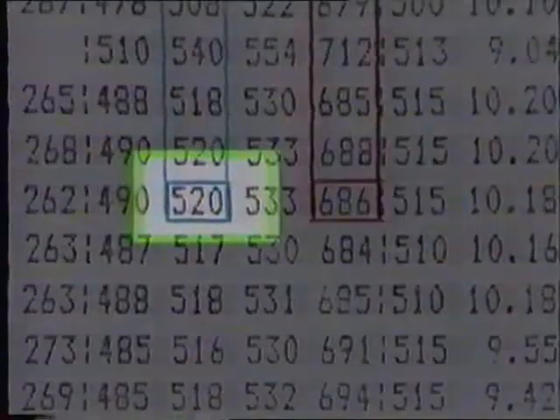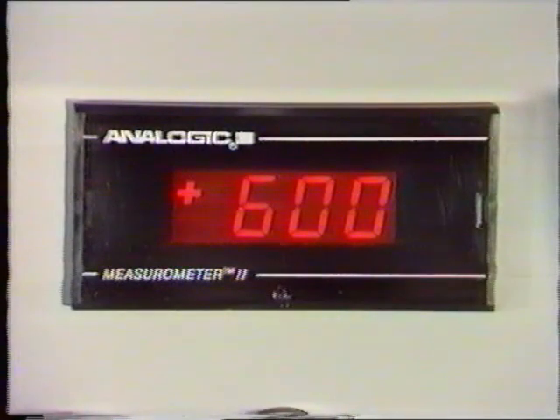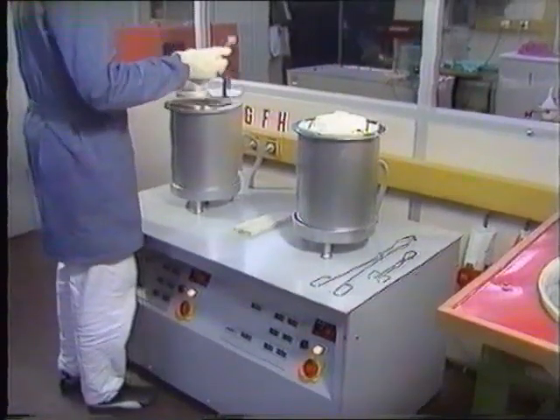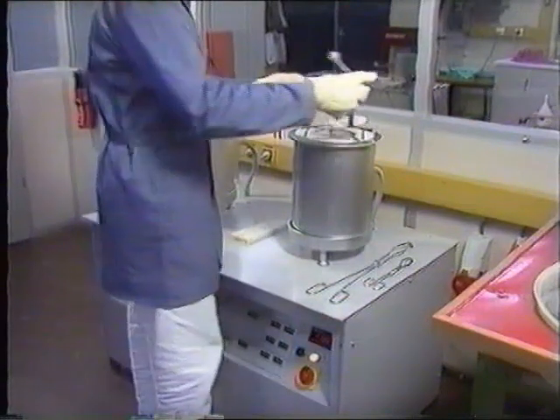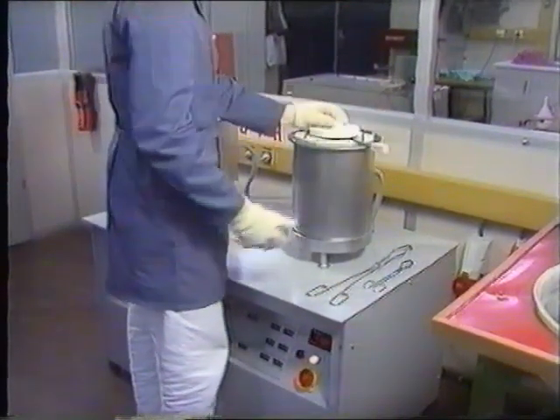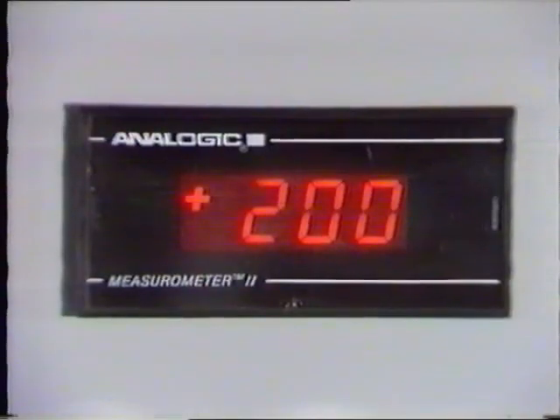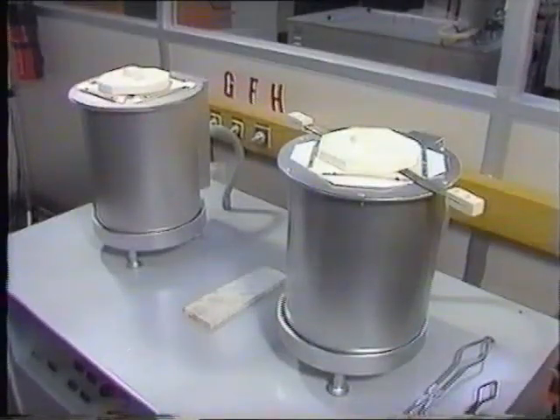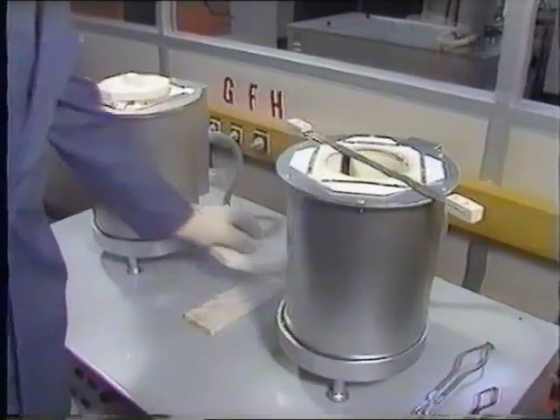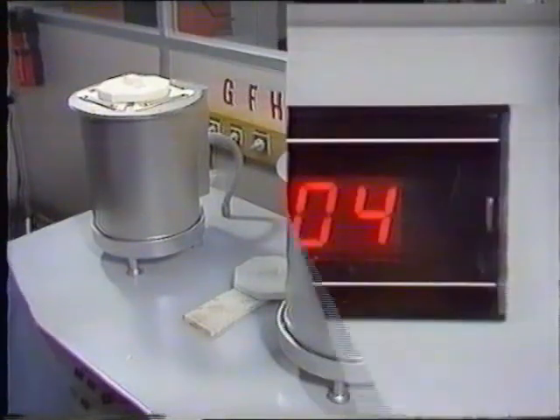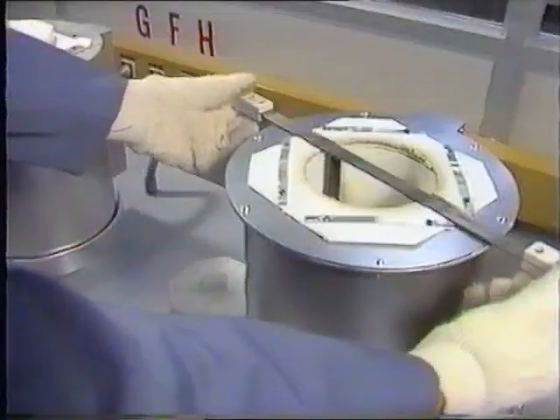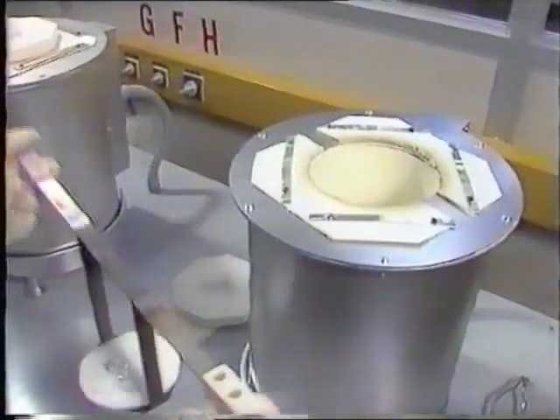The holder is transferred to a second furnace, which has been adjusted to a temperature above the annealing point of the standard glass, dependent on the glass type, of 40 degrees to 80 degrees centigrade. Until a temperature of 600 degrees centigrade has been reached. Now, the cover is removed. At a furnace temperature of about 100 degrees centigrade, the holder is taken out and the sample allowed to continue cooling in the open air.